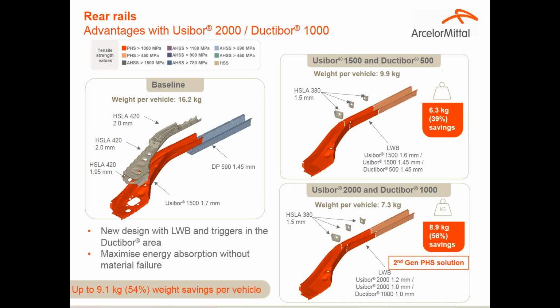First, integration of the patch by adding a welding line, and second, the application of the second generation of PHS steel, the Ductibor 1000 and Usibor 2000. In this specific case, you see that the big patch has been removed and integrated, and smaller patches have been added to cover the stiffness and the crash where really needed, localizing the patches.